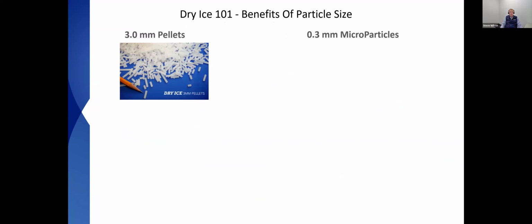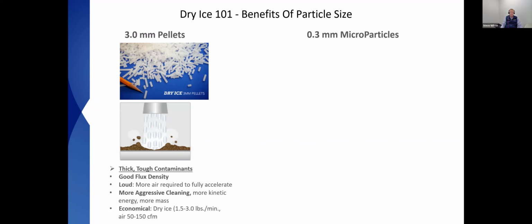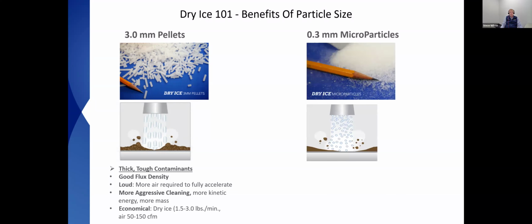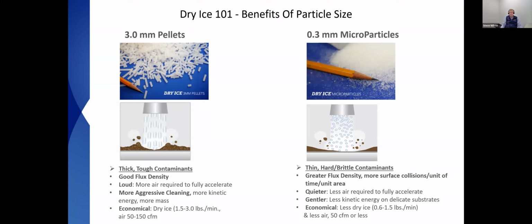Why do I want 3 millimeter pellet over the smaller ones? These are some benefits of particle size. 3 millimeter pellets are very good on thick and tough contaminants. You get a good flux density, but it's really good for cleaning things at ambient temperatures. You get more aggressive cleaning. Because it's 3 millimeter, you're going to feed about 1.5 pounds to 3 pounds of dry ice, and you need 50 to 150 CFM at 80 PSI. Microparticles, you can see, have a greater flux density.